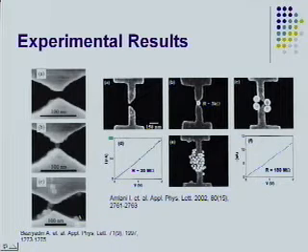Whereas if you have a very small particle compared to your gap size, you get these clusters, or we call them grapes, the shapes that you see on the bottom in E there. Depending on what size you use, you get all sorts of different interesting effects. One hard part is that you don't know when you should stop your trapping experiment, especially when you get one of those grape clusters. You can't really measure how many there are while you're doing this.